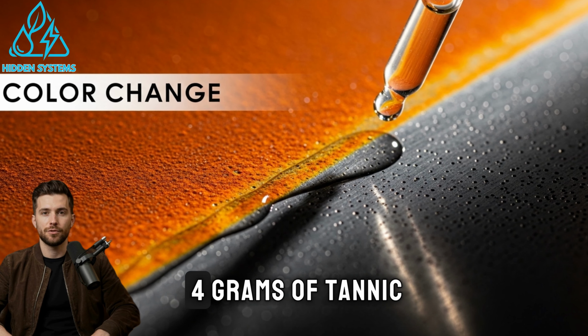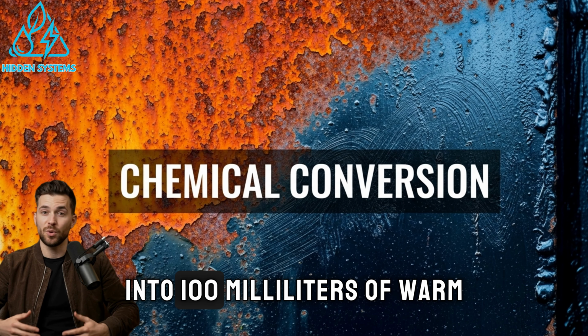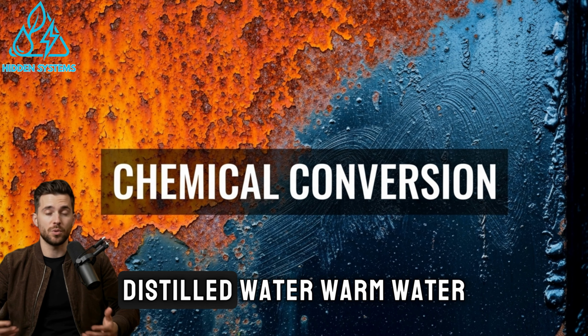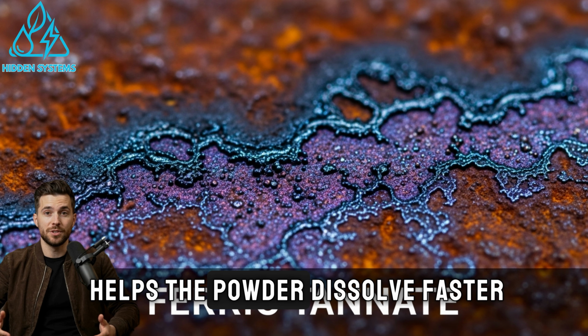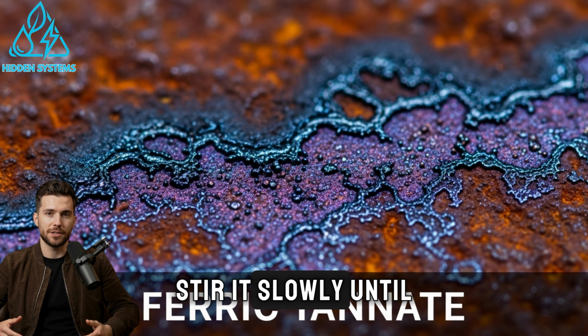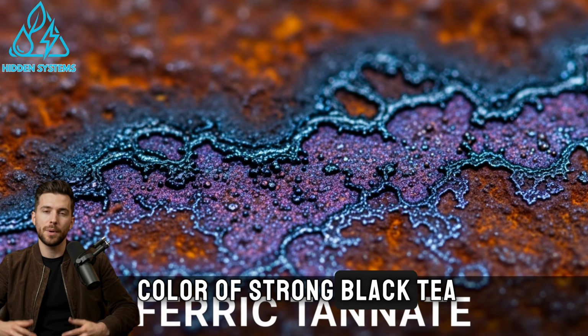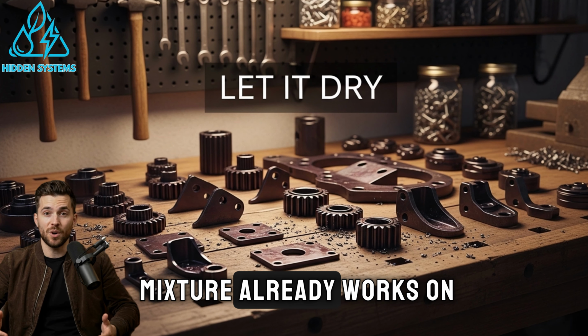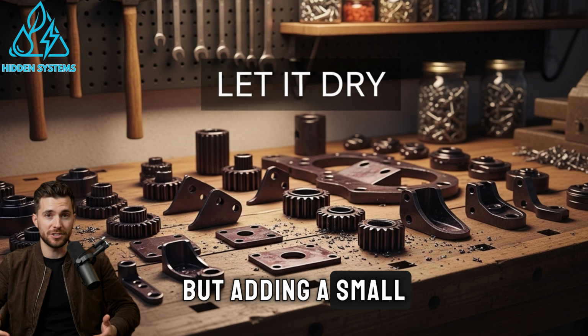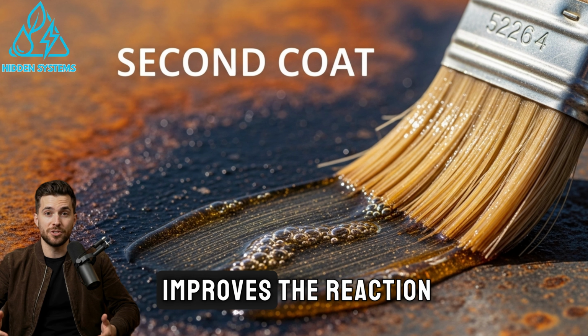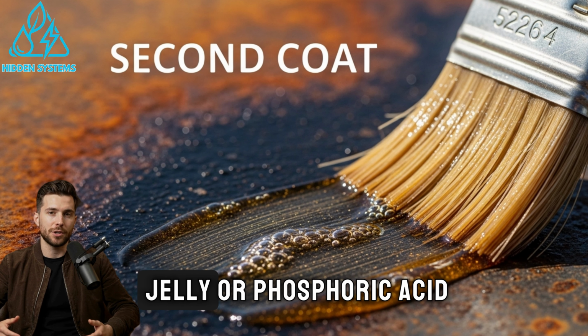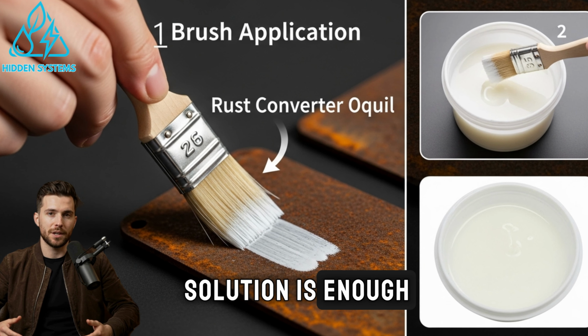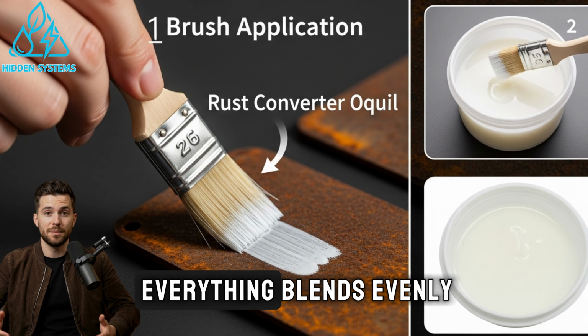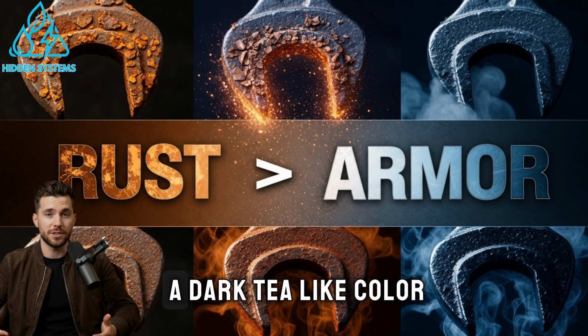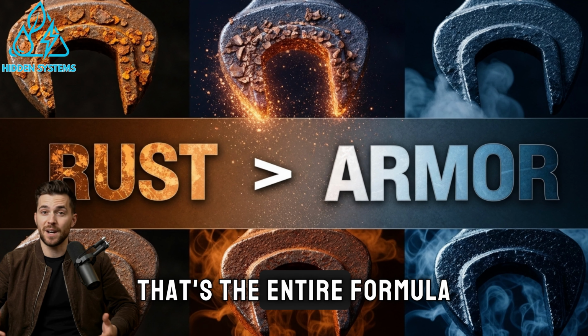Once you have the materials, the preparation is simple. Start by mixing about 4 grams of tannic acid powder into 100 milliliters of warm distilled water. Warm water helps the powder dissolve faster. Stir it slowly until the solution turns the color of strong black tea. At this point, the mixture already works on its own, but adding a small amount of phosphoric acid improves the reaction. A teaspoon of naval jelly or phosphoric acid solution is enough. Stir it in until everything blends evenly. The liquid will remain a dark tea-like color. That's the entire formula.